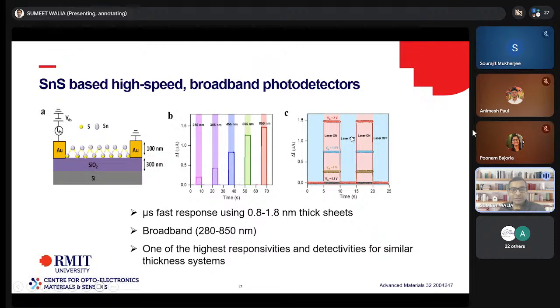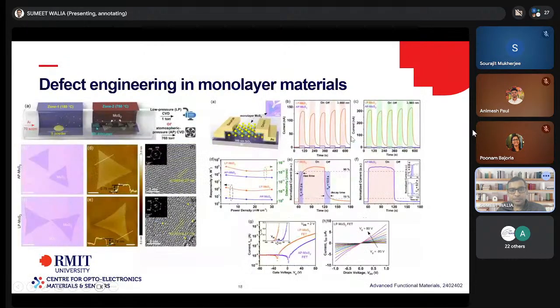the spectrum. So this is some work that we did in creating tin sulfide and showing that this material could be a relatively broadband photodetector, all the way from UV to the near infrared. This was published in Advanced Materials a few years ago. In this particular case, we actually used the liquid metal exfoliation. So we basically had a molten tin in a sulfurized environment where a tin sulfide layer forms at the top, and then you can basically transfer it off as around a 1 nanometer thin tin sulfide.